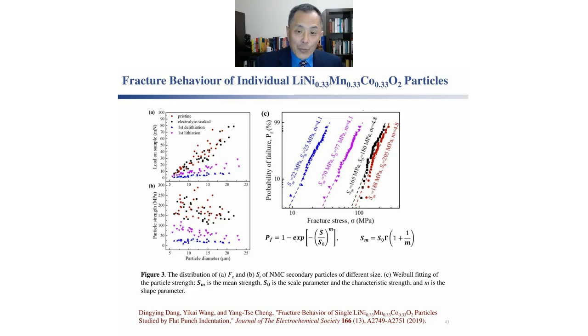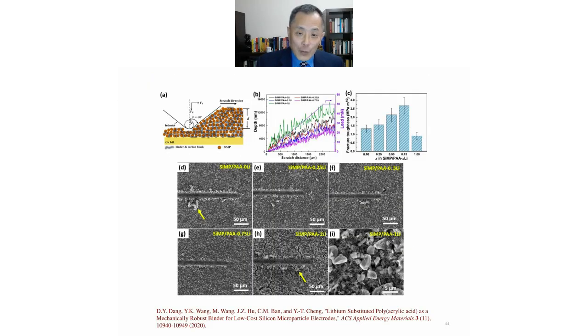In addition to indentation, we are also doing some scratch tests on the electrode. For example, in this paper, we were able to extract the fracture toughness from a scratch measurement using a formula proposed previously in the civil engineering community when they performed scratch tests on porous materials.